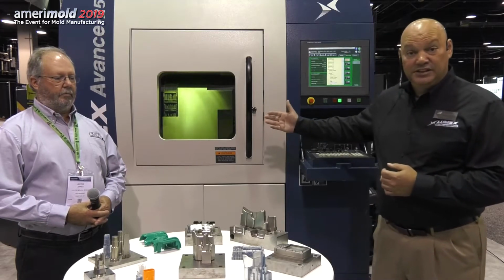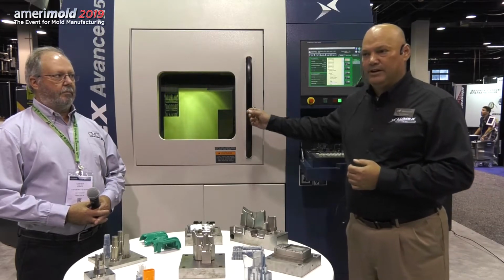On the laser sintering side, our process parameters are designed and developed to achieve full material properties without a hipping or without a heat treatment process. As sintered, they come out at 36 Rockwell. It can be heat aged, 485C for 3 hours to a 53 Rockwell hardness. Perfect application, again, in the injection mold industry.